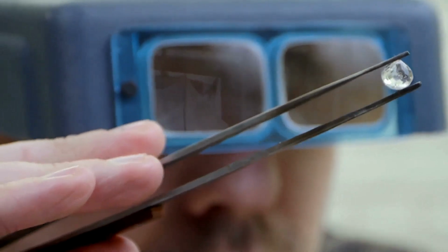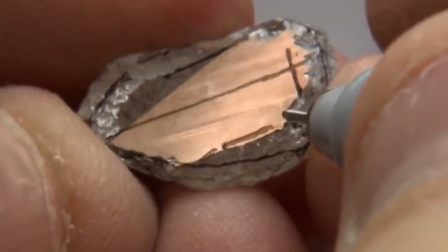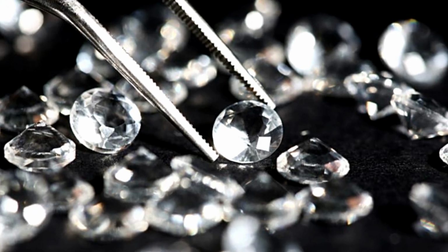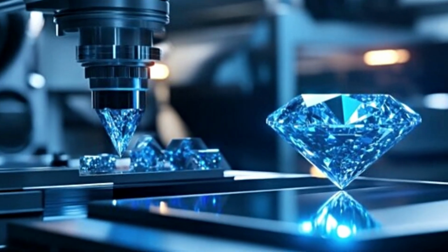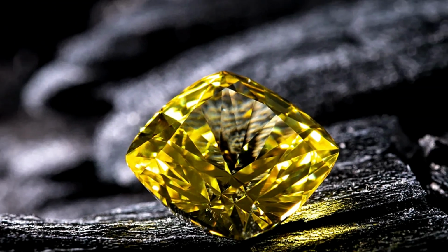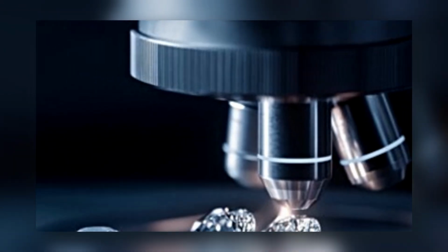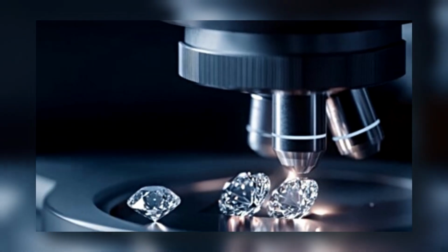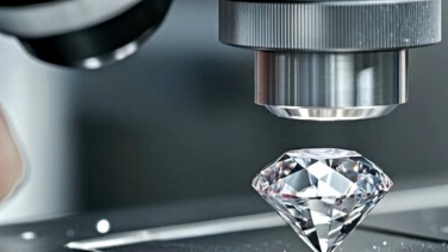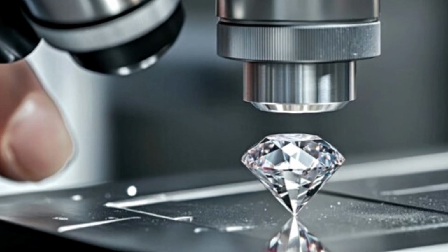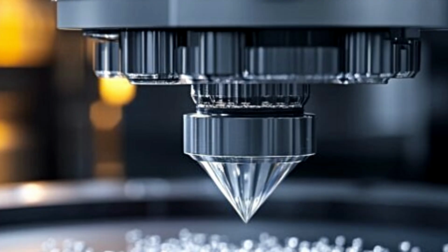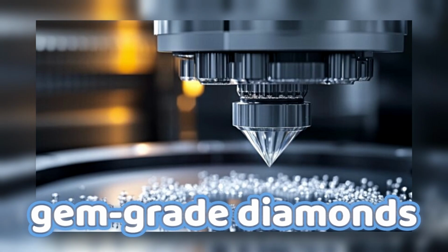HPHT is particularly versatile, allowing manufacturers to produce larger stones or tailor colors by introducing specific impurities, such as boron for blue diamonds or nitrogen for yellow ones. The resulting crystals are analyzed using Raman spectroscopy and X-ray diffraction to confirm their 99% purity and near-perfect lattice structure, ensuring they meet the stringent standards of gem-grade diamonds.